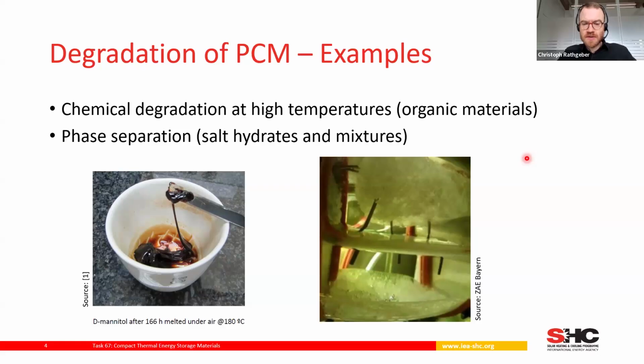A second example, and this is observed for mixtures of PCM or salt hydrates, is phase separation. During repeated thermal cycling, you can observe that different components of the mixture, solids and or liquid phase, separate from each other and do not homogenize again.